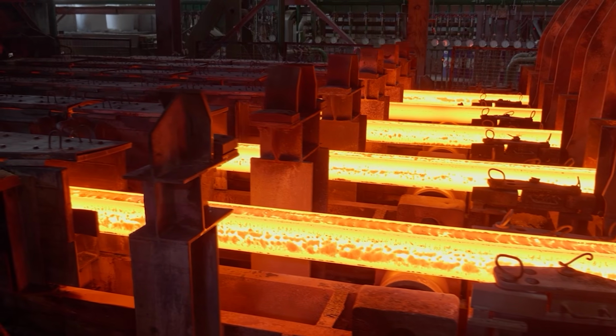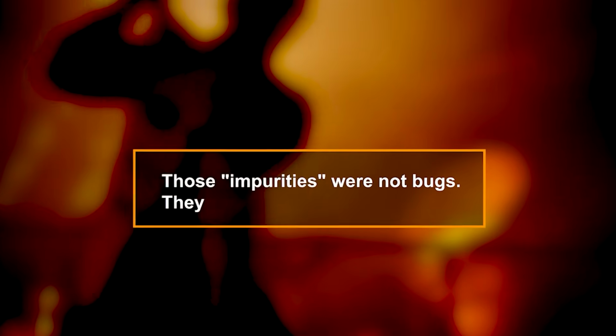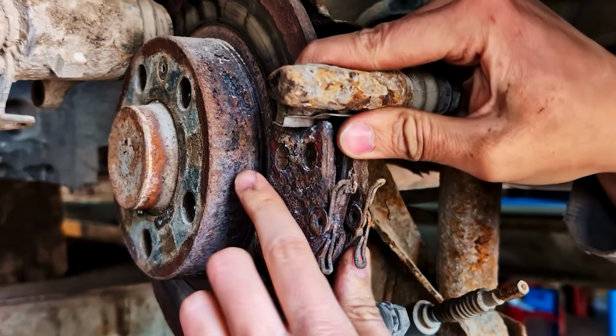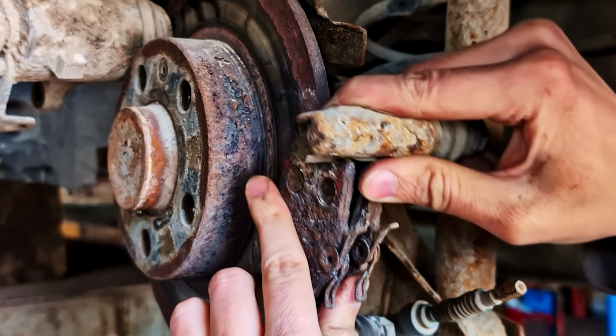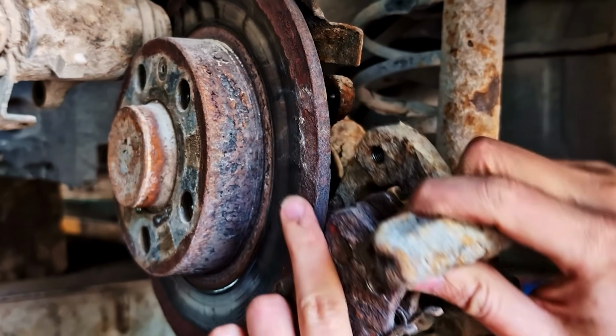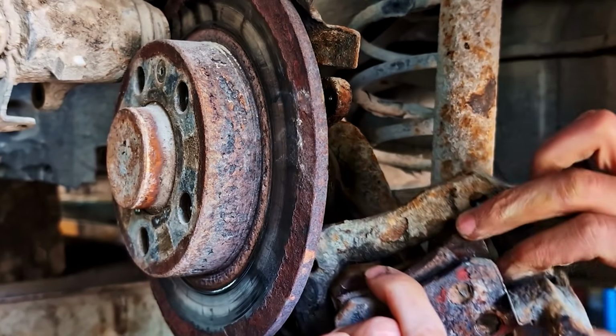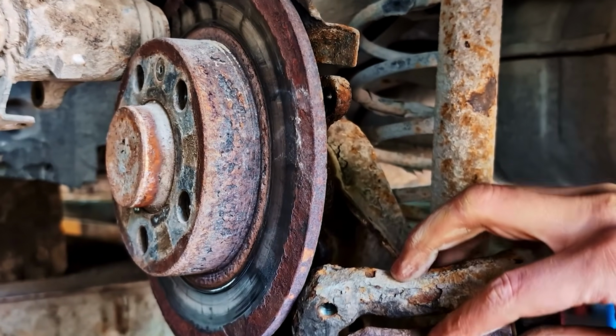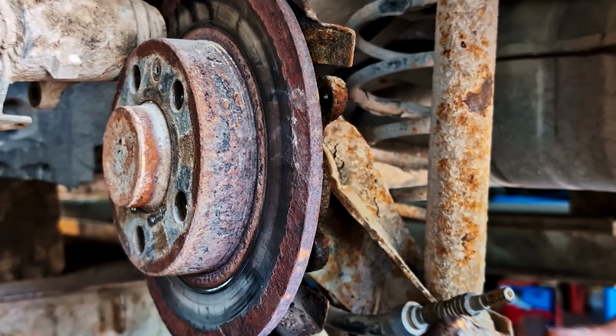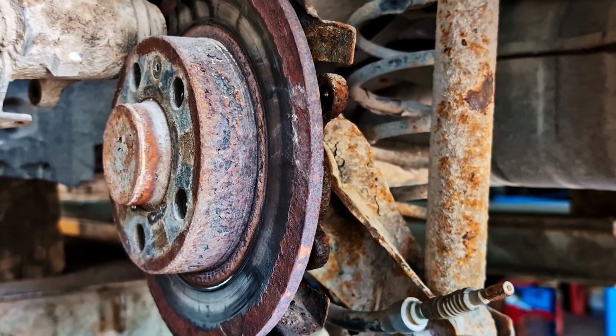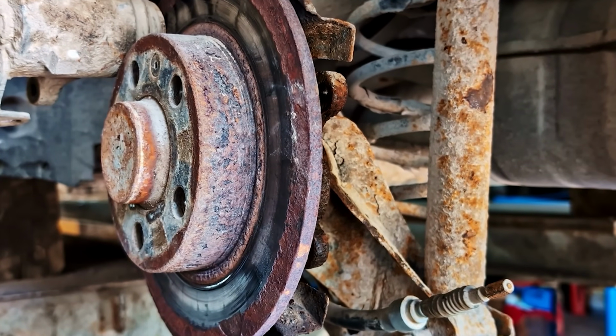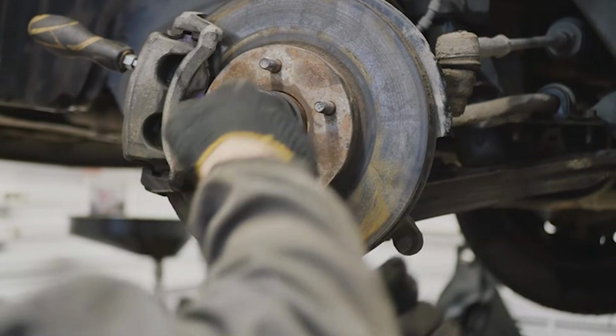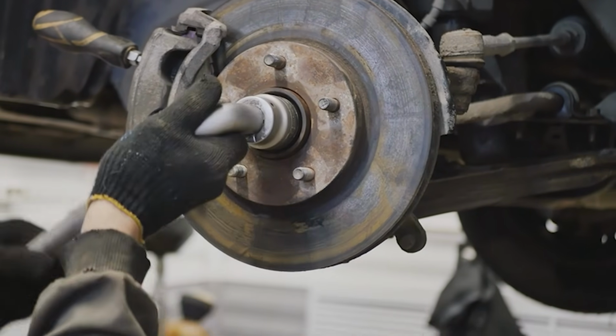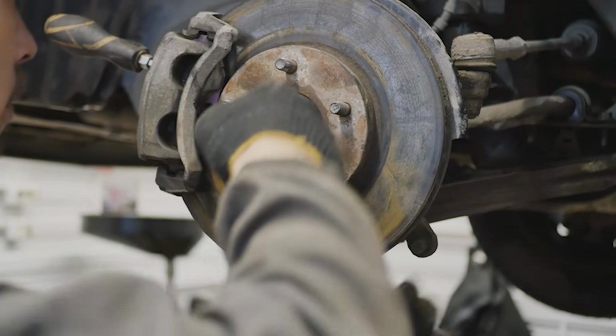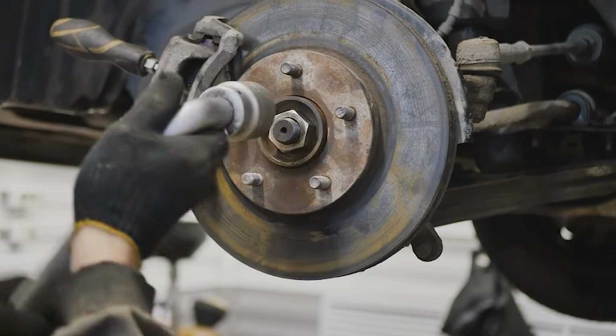But here is what we did not understand until recently. Those impurities were not bugs. They were features. When modern steel rusts, the corrosion digs straight down. A speck of moisture touches the surface. Oxygen reacts with iron. Rust forms. That rust is porous, and it traps more moisture, which creates more rust. The corrosion burrows deeper, following the grain boundaries of the metal like roots following cracks in concrete. A microscopic crack in modern steel becomes a highway for rust. Nothing stops it. Within months, surface rust becomes structural damage.